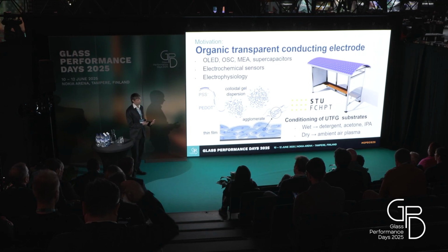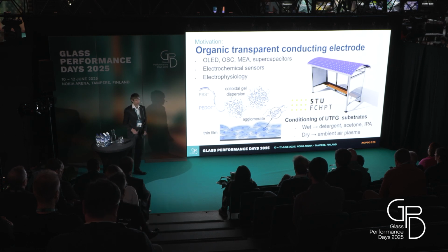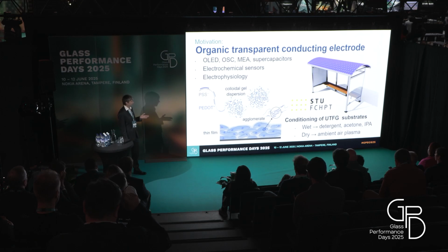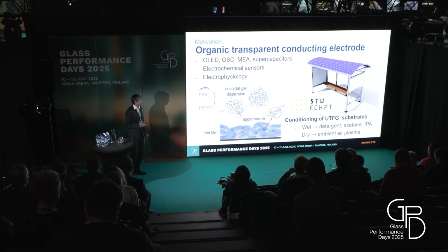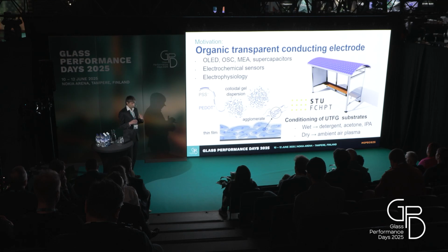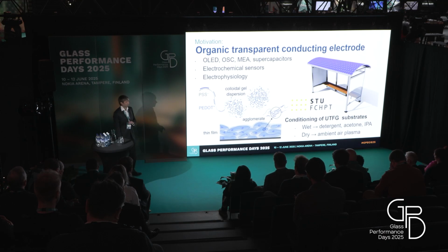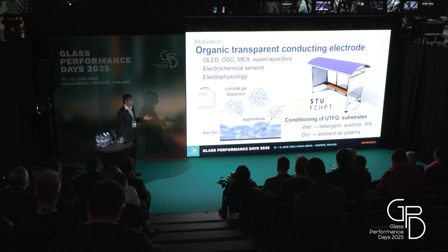And typically nowadays flexible electronics are mostly made with plastic substrates or superstrates, and these cannot act as a barrier as much as, for example, glass can. So the high chemical resistance of flexible glass is a motivation to use it as an encapsulation material for organic coatings like PEDOT:PSS. And the surface energy of the flexible glass is so low that normally the coating cannot be formed on it, because it shrinks into small islands and is not uniform. And for a conductive coating, you need uniformity of the coating, without any defects. So that's why in a solvent-based cleaning protocol, a detergent is used, which contains surfactants that can raise the surface free energy. In plasma, we just used ambient air.